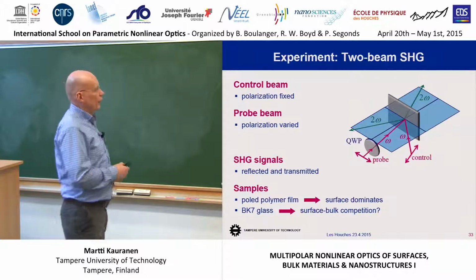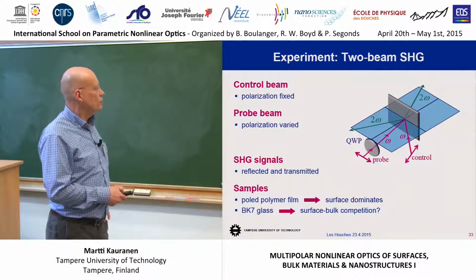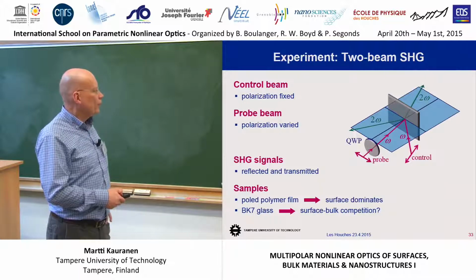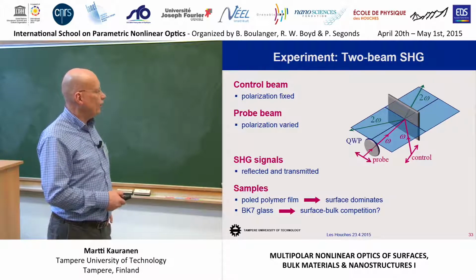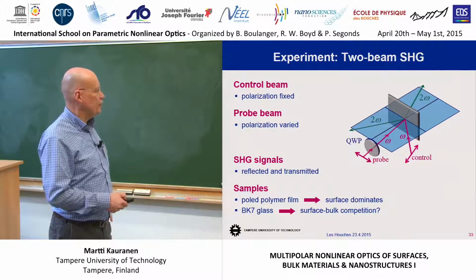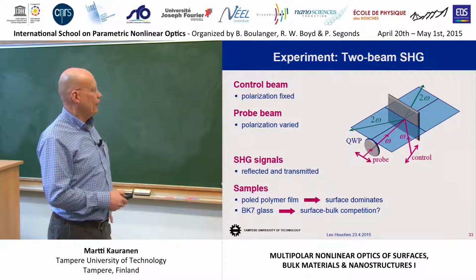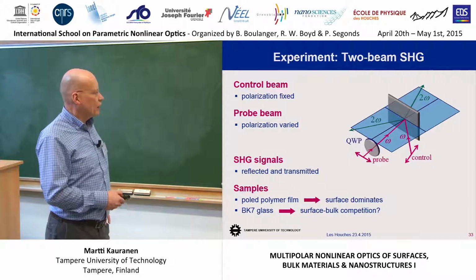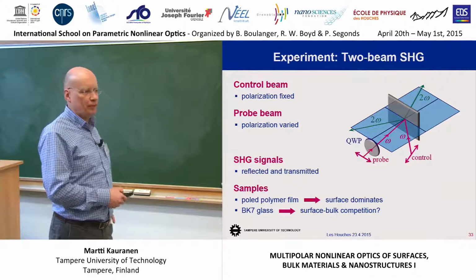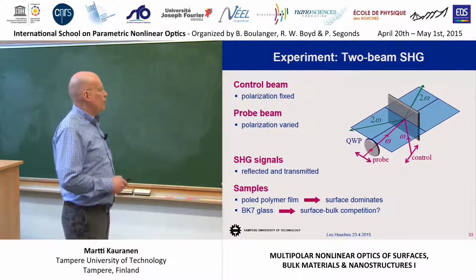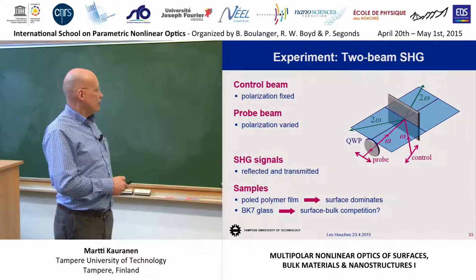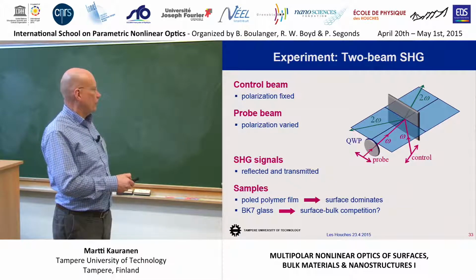So this is the idea of how we do the experiment. Two-beam second harmonic generation. We call one fundamental beam a control beam, the other one a probe beam. Here we fix the polarization of this beam. It could be S or P, maybe plus or minus 45 degrees in between. And then we use a quarter wave plate to modify the probe polarization. Our starting polarization is sometimes S or P, sometimes plus or minus 45 and so on. And we can measure second harmonic signals in the reflected, or transmitted, direction.